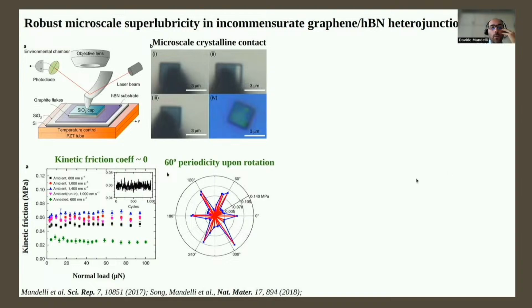We have been collaborating with the experimental group in China, who have performed a frictional experiment of micro-scale flakes of graphite sliding on hBN, and what they observed is that, as expected, a very low kinetic friction independent of the normal load, demonstrating that structural superlubricity can hold up to the micro-scale.